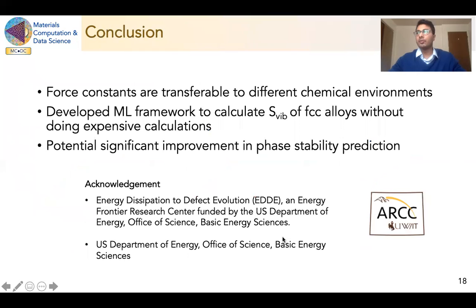So here I want to conclude my presentation. The force constants of all types of bonds are transferable to different chemical environments. We have developed machine learning framework to calculate the vibration entropy of FCC alloys without doing any expensive calculations. Just one calculation is required, which you need anyway for the enthalpy of mixing. So with this framework, vibration entropy can be included in the phase stability, which significantly improves the phase stability predictions.